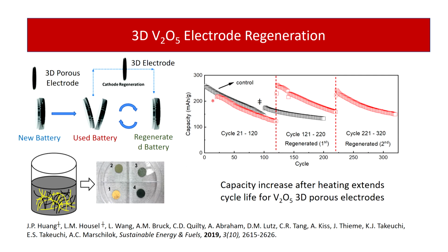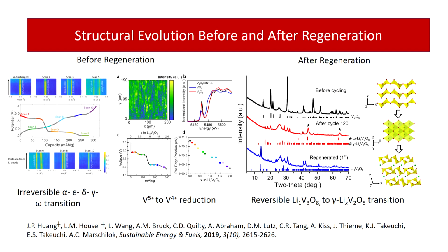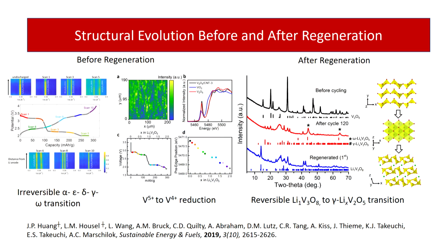And again, we've demonstrated this with vanadium. We've demonstrated this with manganese oxide. So in fact, it works. We've done extensive characterization before and after regeneration to understand the phases that are formed, why this works. We've done mapping, we've done EDXRD, we've done operando XAS. And in the case of the manganese materials that we've looked at, they in fact restore the original structure. In the case of this vanadium material, interestingly enough, the phase that ends up contributing to lower capacity as it originally cycles is transformed under these conditions into something new. We start out with V2O5 and phases of that and end up with LiV3O8, which is one of the materials that I talked to you about. So in fact, we are able to demonstrate regeneration.